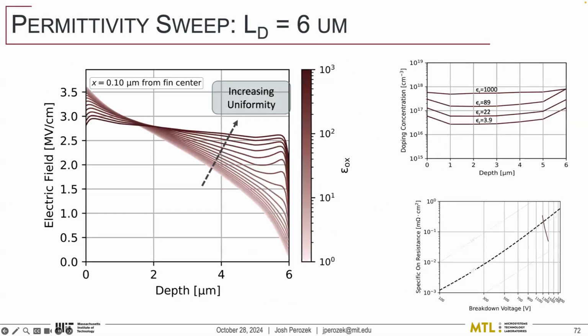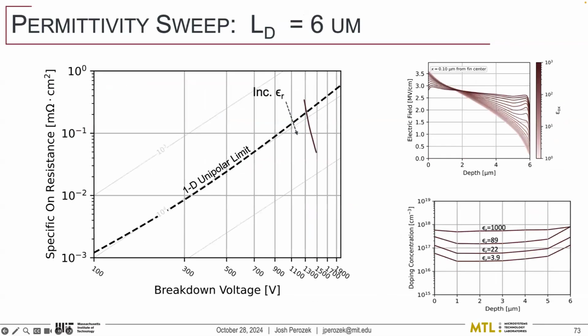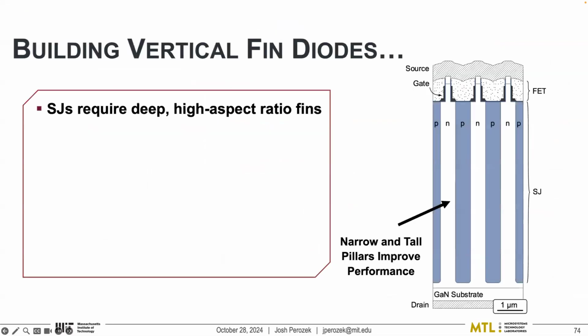As we do that, we also see that our electric field becomes more uniform, like we had talked about, which lets us get a little more breakdown voltage out of these devices. And on that plot that we had shown before, we're able to slowly inch past that 1D unipolar limit. And again, I should stress the log nature of this plot. It doesn't look like that line moved very far, but it's a pretty substantial improvement in terms of your on resistance. So we know what we need to make.